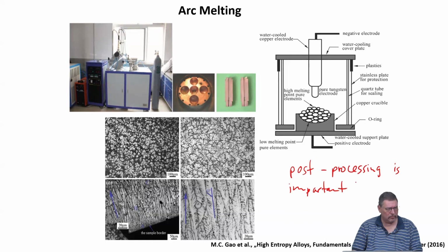I recommend not only to do homogenization treatment, but once you have melted the alloy several times so that you have compositionally homogenized the alloy, it's normally a good method to severely deform the material by rotary swaging or by hammering, whatever, and then do the homogenization treatment. Or maybe do homogenization annealing, then deformation, and then again relaxation or recovery annealing, because that will give you not only compositionally uniform material, but also microstructurally the material will be much more uniform, as if you do not include this mechanical plastic deformation treatment in between.